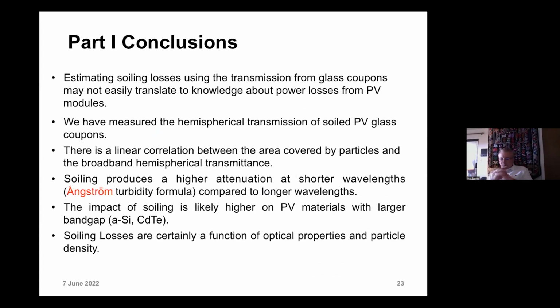Okay, so I see at 18 minutes after the hour that I have some time for some conclusions. I hope that I've impressed upon you that estimating the soiling losses using the transmission from a glass coupon may not easily translate to knowledge about the power loss from PV modules. We've measured the transmission of soiled glass coupons for a first step. And we find that it adheres to a modified form of the Angstrom turbidity equation.